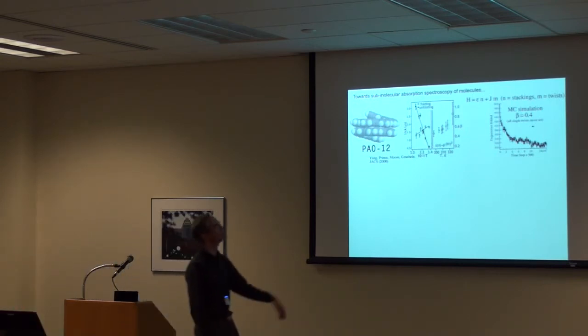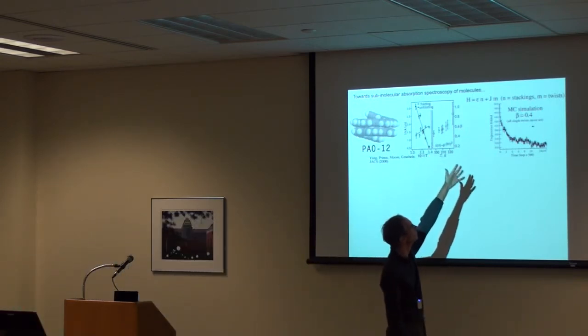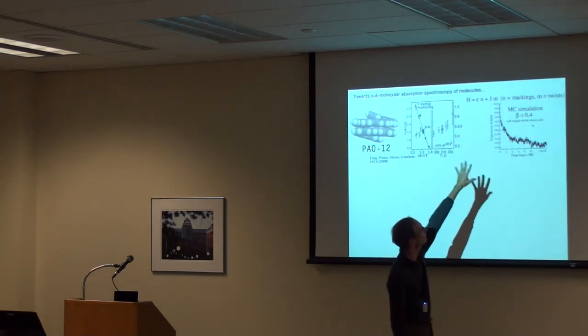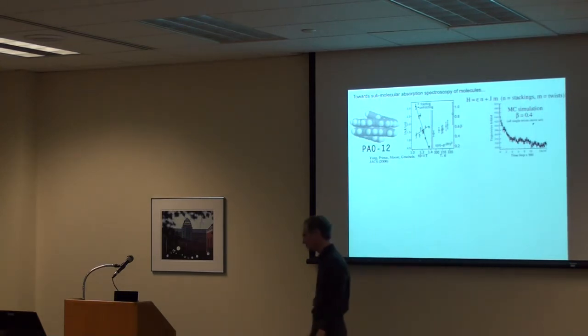And when you ran pseudo Monte Carlo kinetics with a reasonable move set that would look like the real moves that the molecule can do, we were actually able to reproduce this kinetics that consists of these very fast phases initially followed by much slower phases, which gives you this kind of stretched behavior.